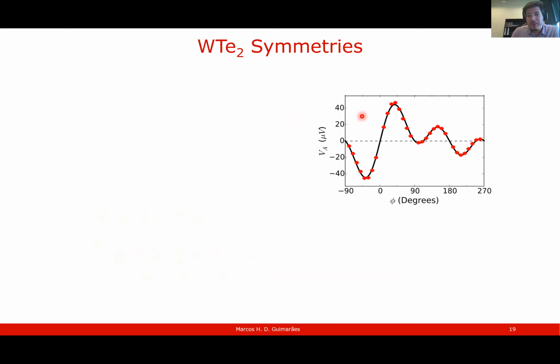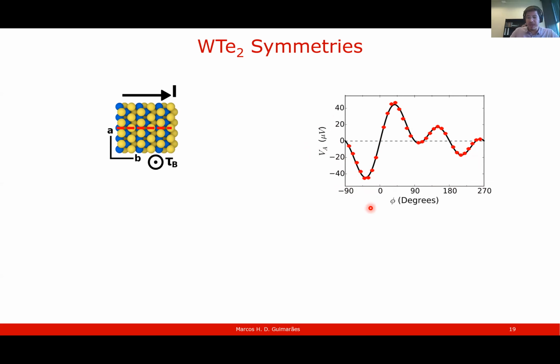So now if we map the antisymmetric component of that resonance curve as a function of the angle of the magnetization, then you can see that it has this funky behavior. And this can be explained, as I told you, by the symmetries of the tungsten ditelluride. So the fact that this dip here, at around 220, is not the same amplitude as the dip at minus 45, is due to that out of plane anti-damping torque.